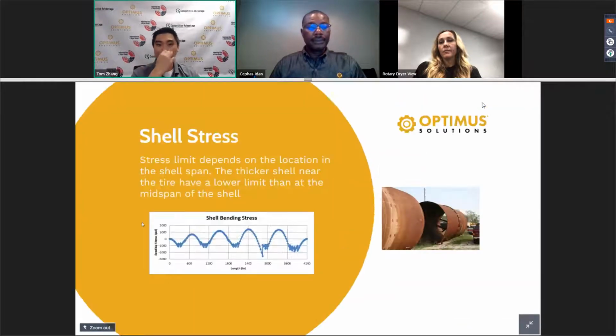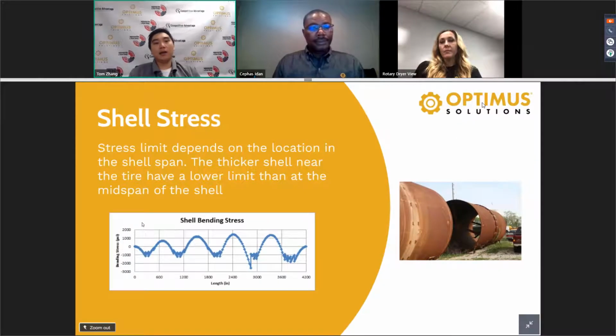Okay, so let's see, what's next? Shell stress. We have interesting things with the shell stress. So industry rule of thumb is about 3,000 psi on the stress of the shell. That's actually the mid span. So on a kiln between, let's say, the first tire and the second tire after that, the uphill tire, it's roughly in the middle. That's where it can have 3,000 psi. It's allowed to have the most load.